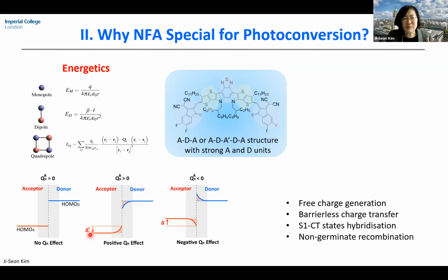And because this is a very short range and strong intermolecular induced interaction, when you come from the bulk to nearer the surface, this quadrupole effect will disappear, producing this quadrupole electrostatic potential induced band bending, which will influence your photophysics when you use this molecule. Another important thing to consider is the electronic state. Of course, you create the excitation through photo excitation, so creating this charge transfer type of state.